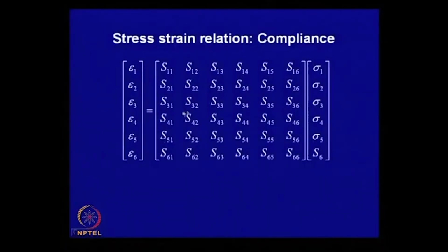So, for example, what does it mean? A cubic crystal has 3 four-fold symmetries. That means if you rotate it about one crystal axis, let us say the crystal axes are usually represented as a, b, c, as has been mentioned, so about a, if you rotate it by 90 degrees, it comes to occupy exactly the same position. In that case also you can convert this matrix to that, and each of these elements will be equal.